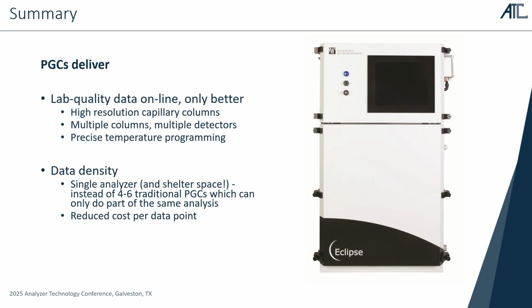So in all, what we found was that we were able to control our pressures, our flows, our temperatures, multiple detectors, and multiple ovens at the exact same time, and get consistent quantified peaks with good separation and good resolution. This allowed us to have all of this in a single analyzer, which helps to reduce some of the cost per data point shown.